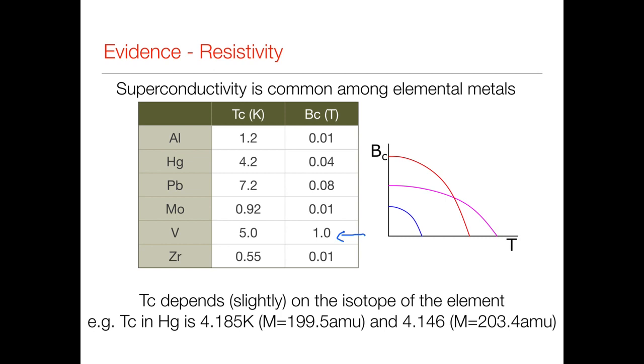Now, the other thing that was found by some really very careful measurements is that the transition temperature depends on the isotope of the element. So it's possible, for example, to isotopically enrich a sample of a metal. We can have a sample of mercury containing one particular isotope and another containing a different isotope, and then we could mix between the two so we can control the weight of the atoms involved. And that does make a difference. The slightly lighter mercury has a slightly higher transition temperature.